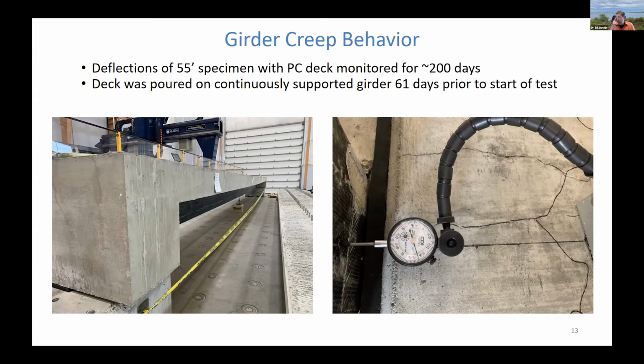And we monitored deflections of that single beam with dial gauges for about 200 days. And that deck was poured on a continuously supported girder 61 days prior to the start of the test. So it had the concrete on there that may have been shrinking and undergoing some deformation, but the girder itself couldn't really deflect because it was continuously supported. And then we basically had it brought into our lab and we took the supports out from under it and started reading deflections on that girder.